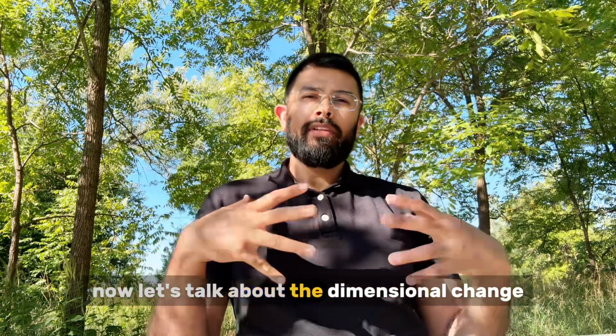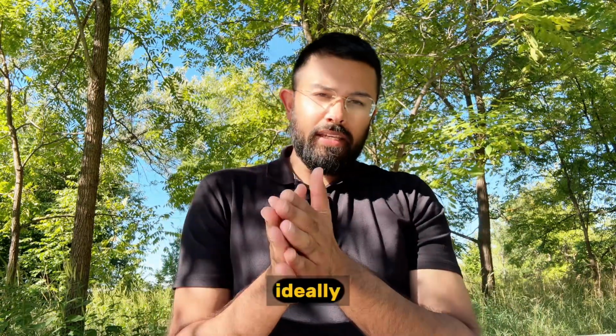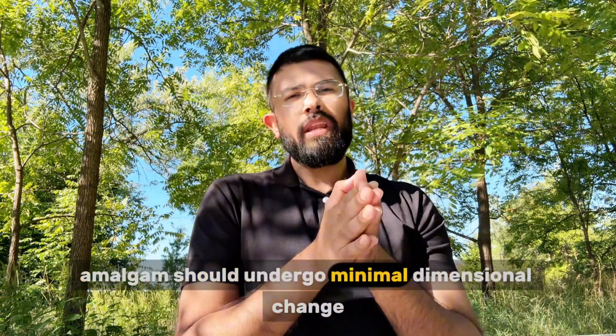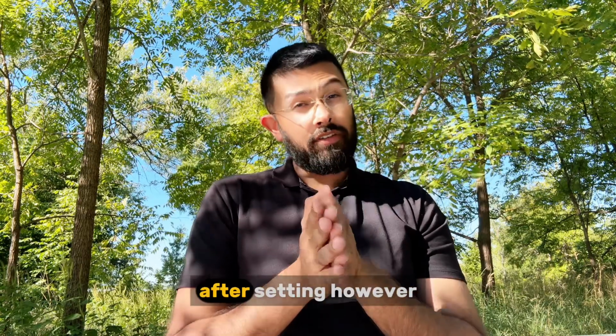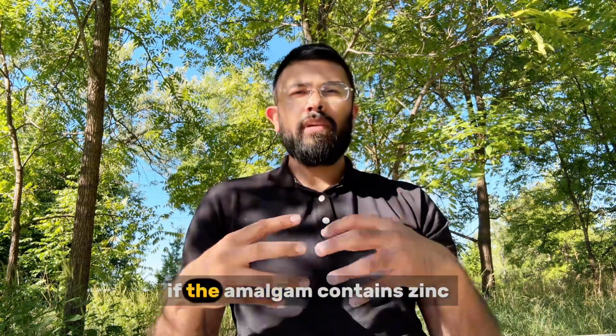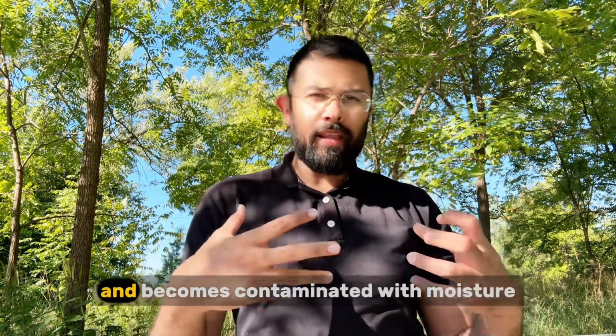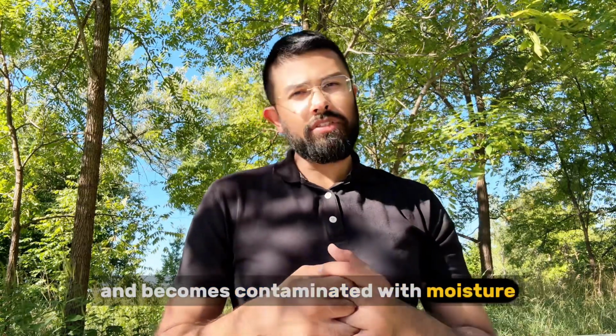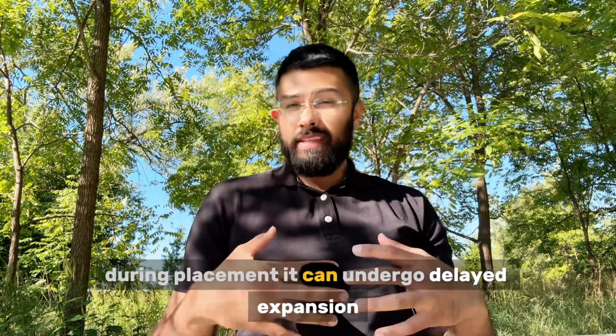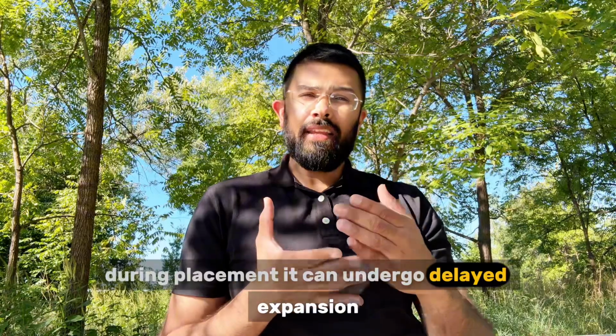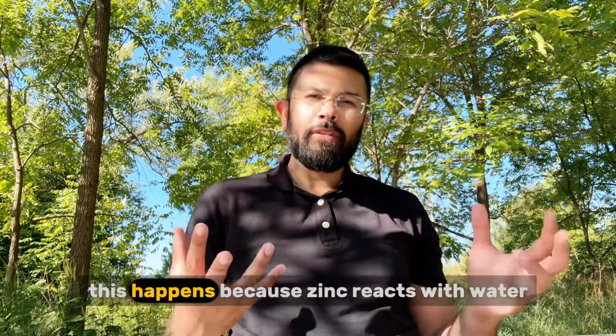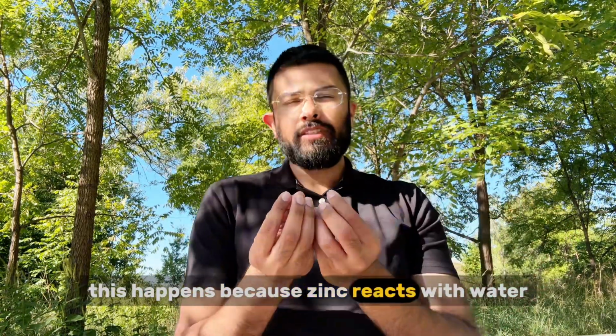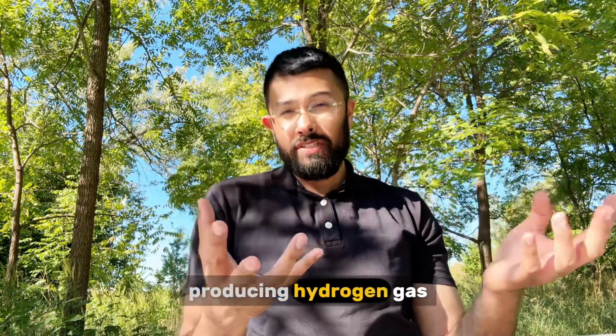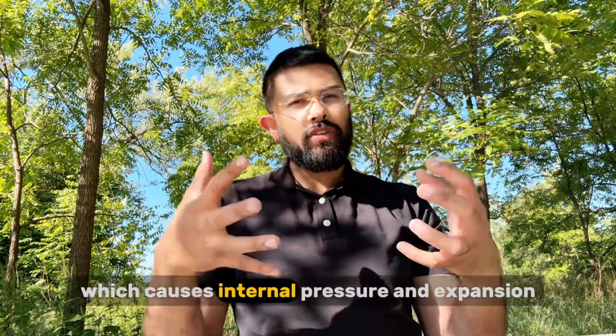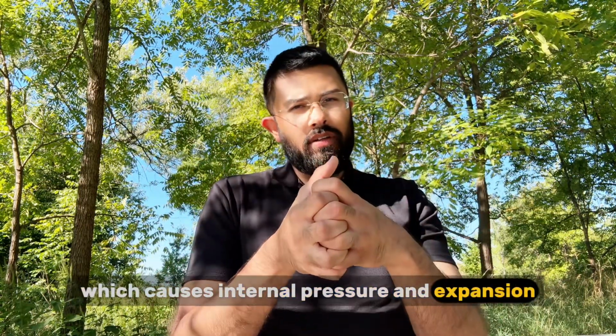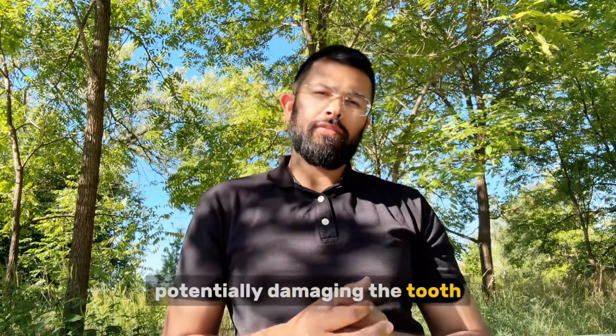Now let's talk about the dimensional change. Ideally, amalgam should undergo minimal dimensional change after setting. However, if the amalgam contains zinc and becomes contaminated with moisture during placement, it can undergo delayed expansion. This happens because zinc reacts with water, producing hydrogen gas, which causes internal pressure and expansion, potentially damaging the tooth.